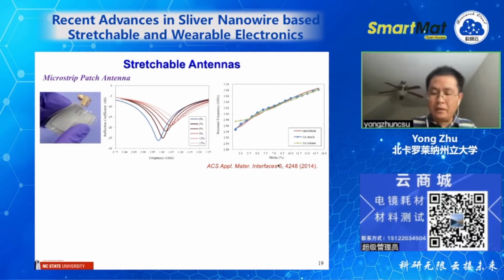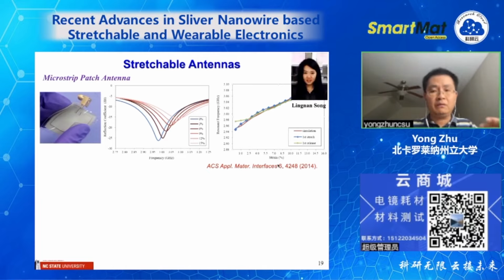Antenna performance depends on two things. One is the high conductivity of the conductor. Two is the loss of the dielectric layer. You want to have less loss. Because this material is very conductive, we were able to achieve a high performance conductor.